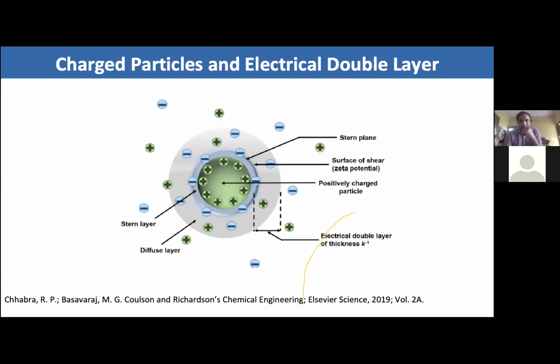In the case of charged particles, the charges are typically expressed in units of surface potential. For all practical purposes, one measures a quantity called the zeta potential, which is the potential at the plane of shear. This quantity is used to infer the stability of colloids in a fluid. That means if the zeta potential is very high, the particles are stable. If it is zero or very close to zero, the particles exhibit limited stability. And as we go on, I'm going to mention that this zeta potential is one of the important factors that affects the processes involved in evaporation of particle laden fluids.